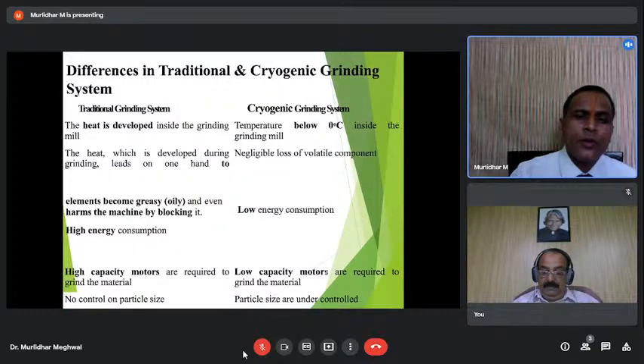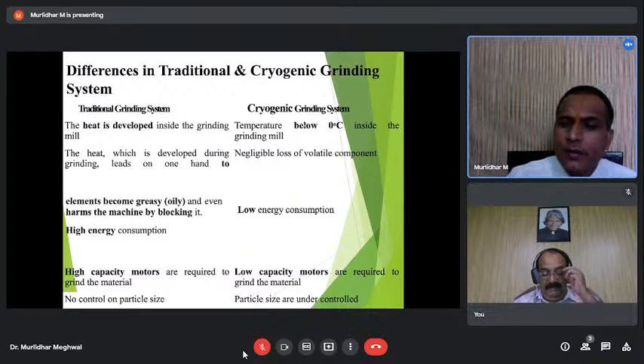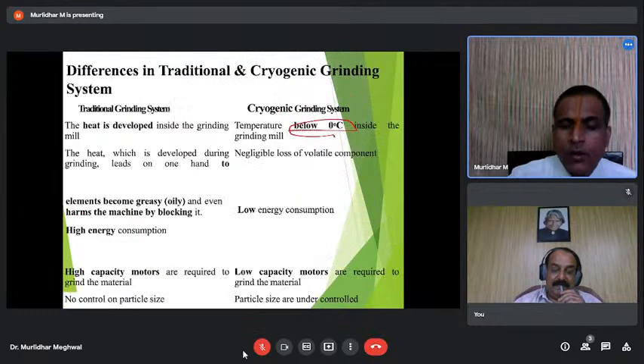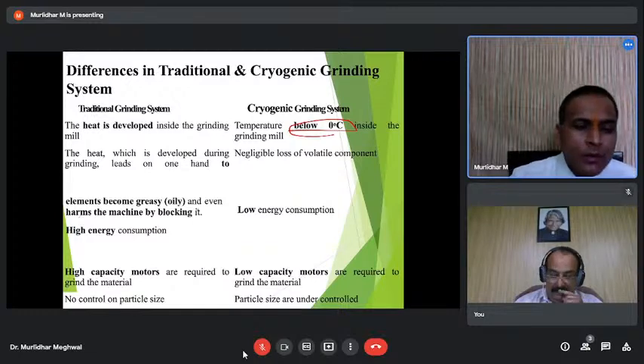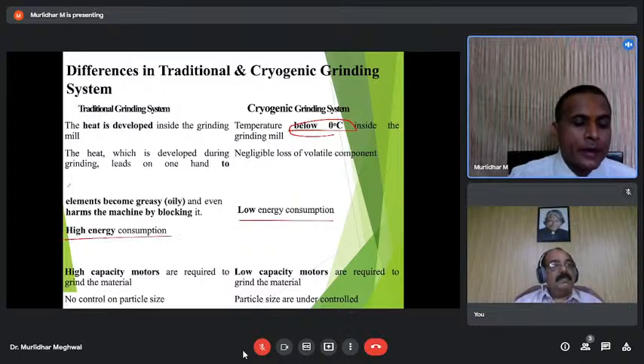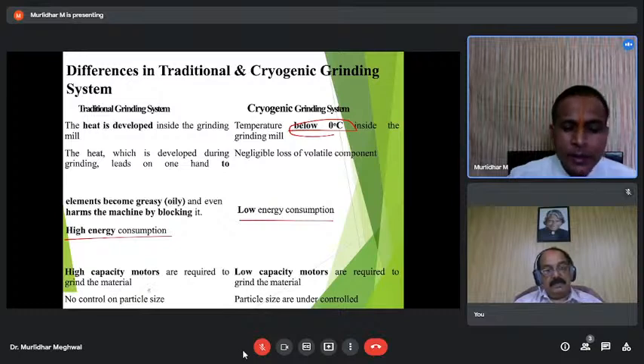If we compare the traditional grinding system and cryogenic grinding system, we see that in the traditional system, heat is developed inside the grinding mill, and that heat will lead to loss of the quality of the spice. Whereas in the cryogenic grinding system, the temperature is below 0 degrees Celsius, and the effect on the quality is less. In conventional or traditional grinding, there are problems like blocking and gumming due to oily materials. Those problems are not there in cryogenic grinding. Another challenge in traditional grinding is the high energy consumption, but here energy consumption is less. In traditional grinding, high capacity motors are required for grinding the materials, but here a low capacity motor works. Control is difficult on particle size in traditional grinding, but here we can control it nicely.